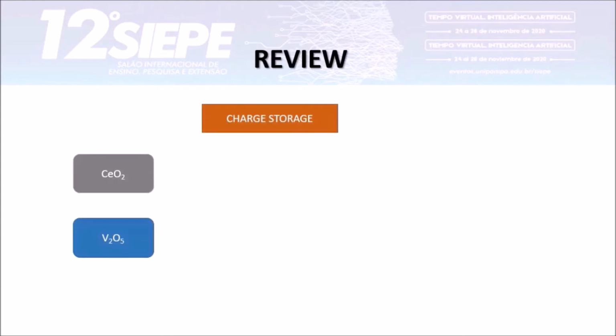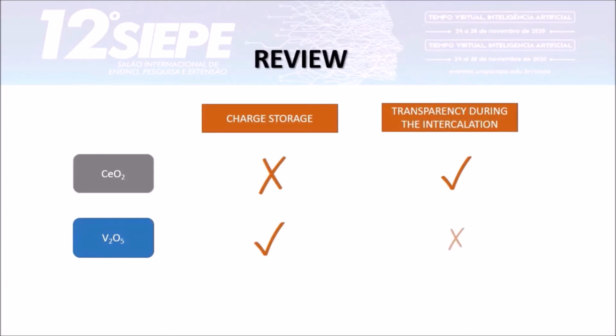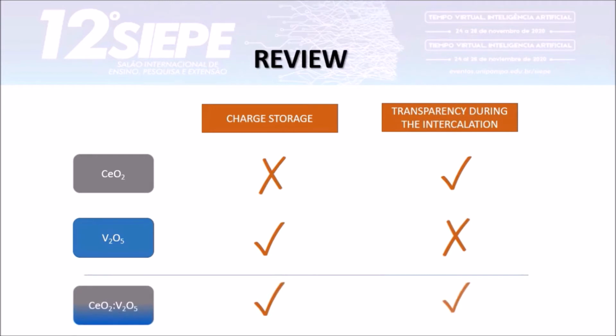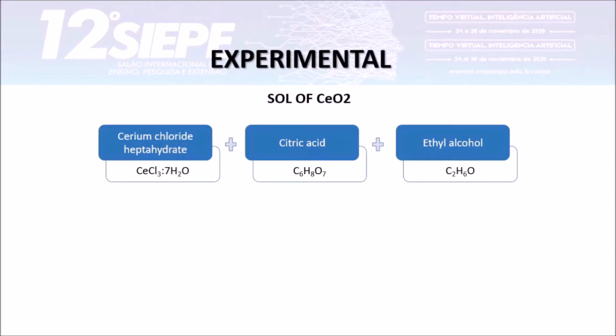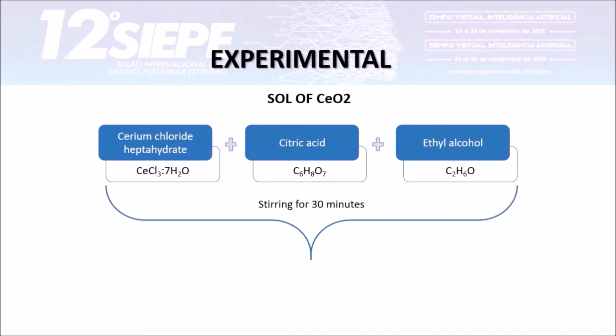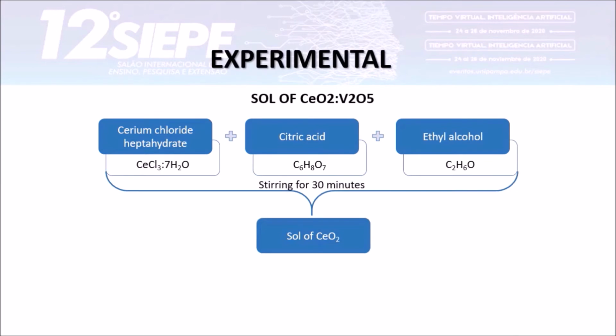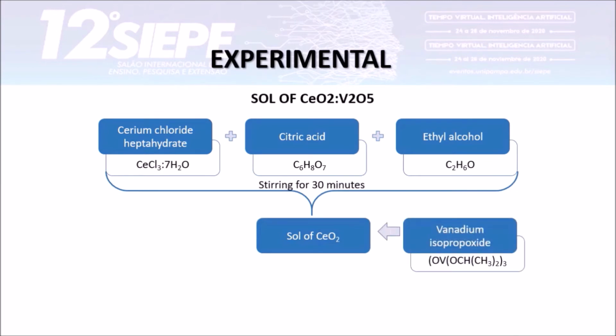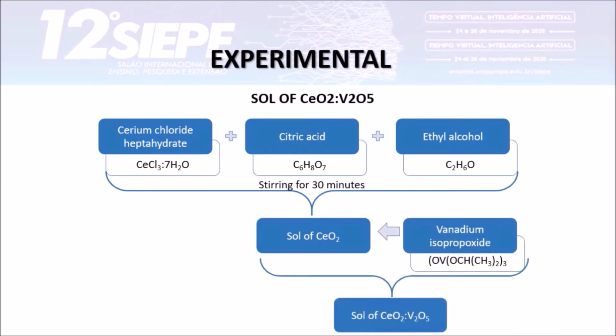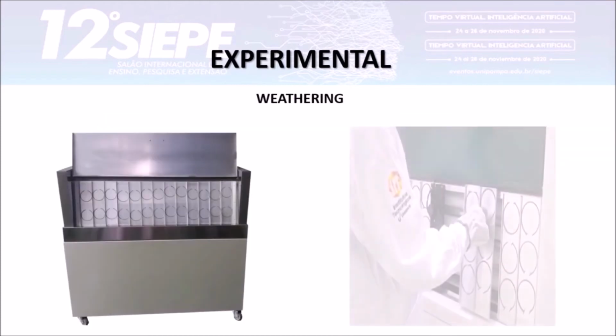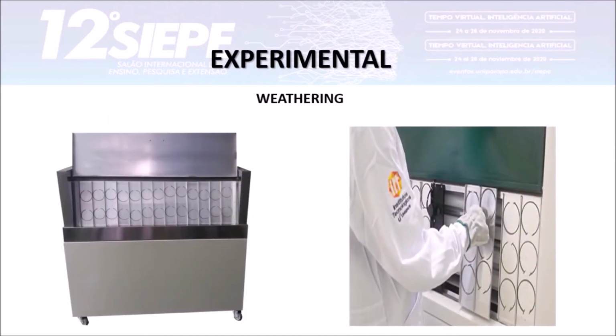Cerium dioxide has good transparency during the intercalation, and vanadium pentoxide has good charge storage. By combining these two materials, we can work with both properties. For the preparation of the sol of cerium dioxide, cerium chloride heptahydrate, citric acid, and ethyl alcohol were stirred for 30 minutes. For the sol of the doped film, vanadium isopropoxide was added to the first sol and stirred for 10 minutes. An accelerated weathering chamber was used to simulate the exposure of the films to the environment.